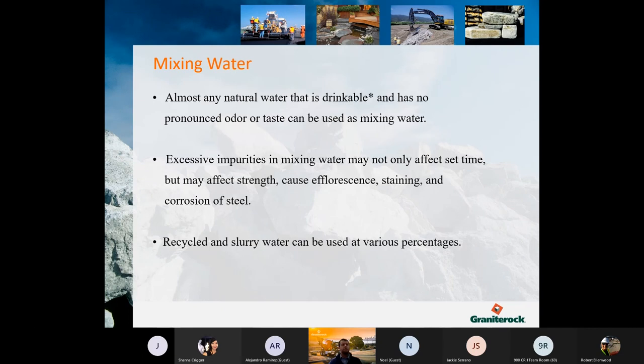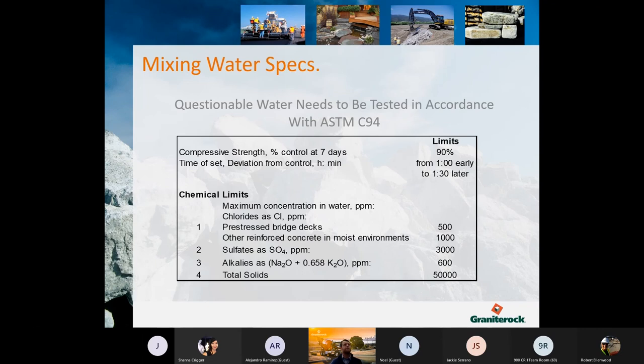You can use recycled or slurry water, but it depends on how much. There's also standards to help govern that. So what you have to do is test concrete, taking the control, and using any recycled water. It has to be the same strength within 90% at 7 days, or the set time has to be similar, either 1 hour early up to an hour and a half after control.